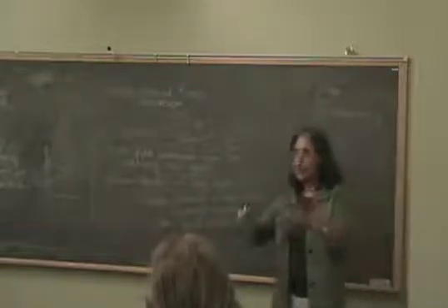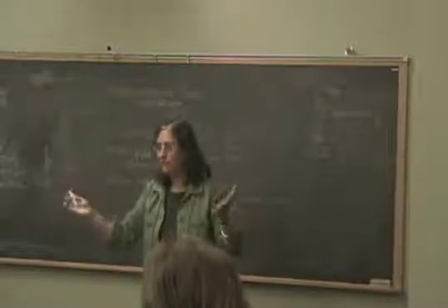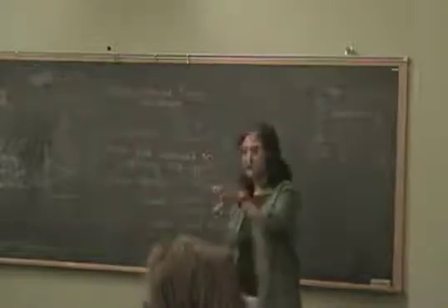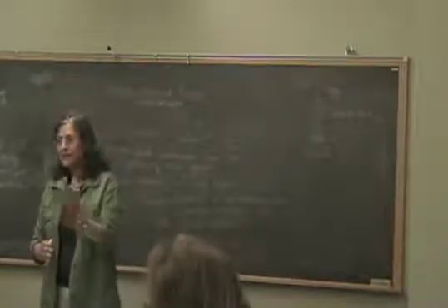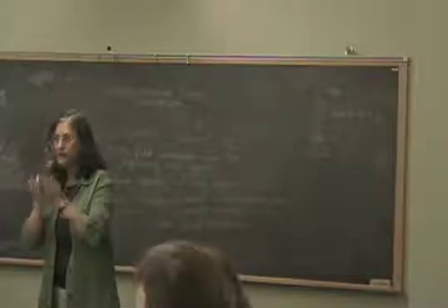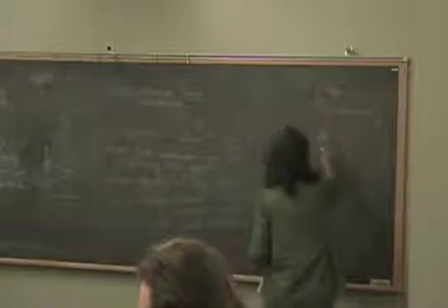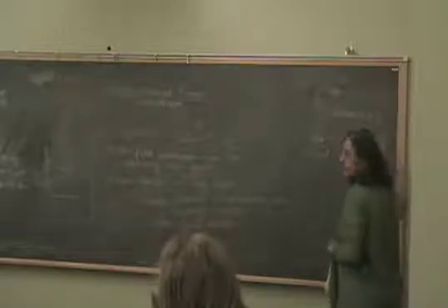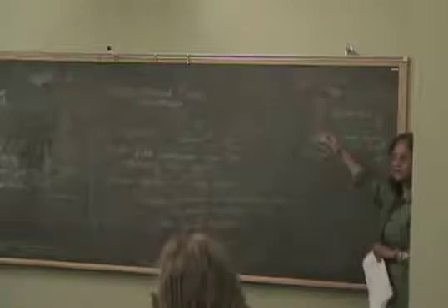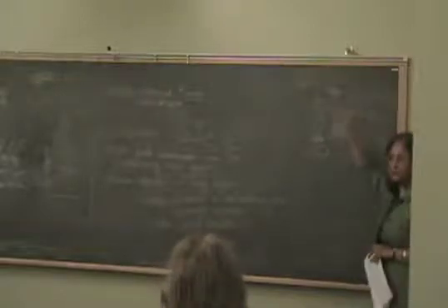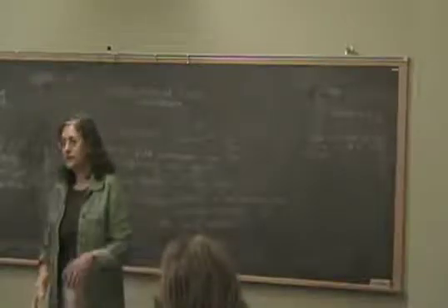The laser has some intensity, and it has some electric field. Of course, overall, you're not violating any energy conservation. It's just that all of that electric field is concentrated at some point. So the metal sphere is used for the following reason. It's used to excite these surface plasmons. That's one reason. And then the shape is controlled to make it lightning rod-like, to concentrate the electric field. So with that, the input becomes very intense. This is an intense source of electric field. That's the 10 to the 6 enhancement of the initial electric field. Then it couples to the vibrational modes of the molecule, and then you can see the shifts and read off those shifts from there.